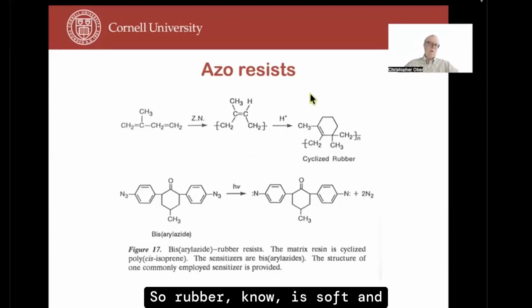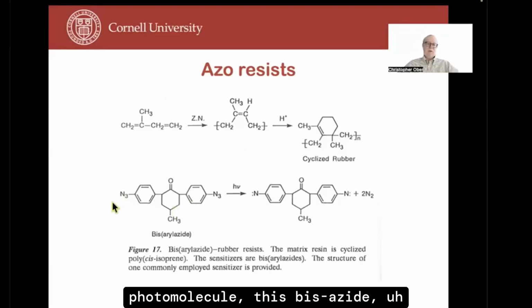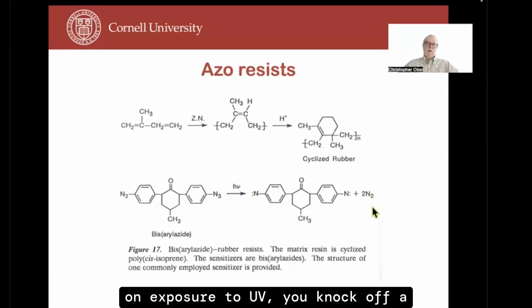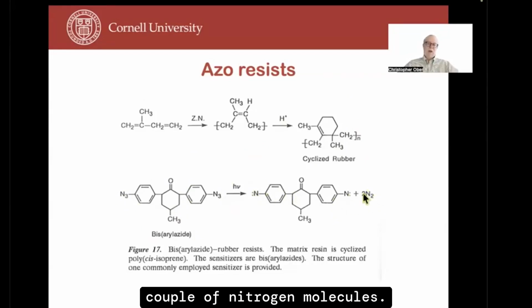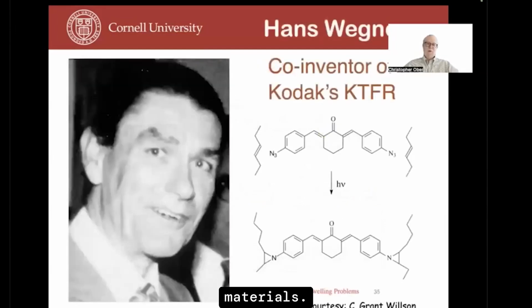So rubber is soft and squishy. By this acid treatment, it made it a harder material. You want that hardness in order to retain the patterns that you produce in it. You don't want it to flow. And using this interesting photomolecule, this bis azide, on exposure to UV, you knock off a couple of nitrogen molecules. You're left with this very reactive nitrogen that can go after the double bond and stitch it all together. So these are negative tone resist materials.